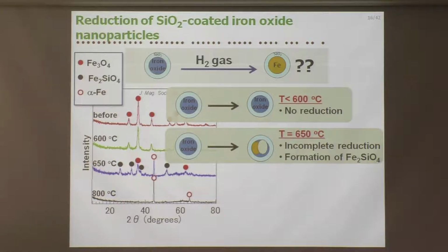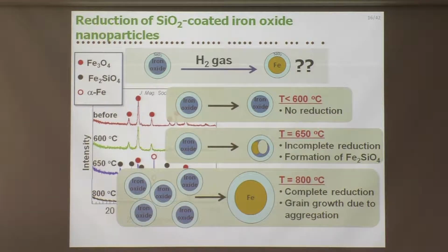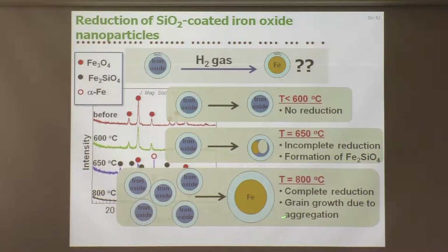However, as you may find, the width of the diffraction peak is very narrow. This means the formed alpha iron particle is very big. So at this temperature, we can obtain complete reduction, but grain growth due to aggregation occurs.